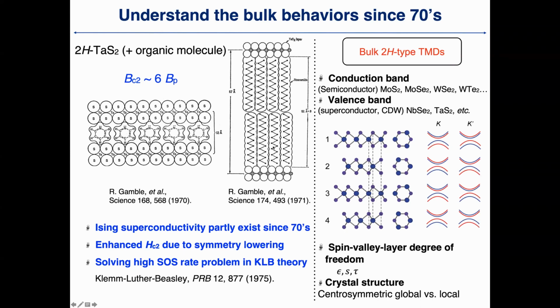So there are 2 effects. One is the local spin orbit interaction and the layer index. Because of the layer index, this K and K prime spin texture actually flips with each other. So this blue spin is flipped with this red spin for the second layer. So if you study a bulk, this Ising protection gets cancelled. But then if we can have a mechanism to decouple the layers, then this Ising protection starts to appear again.